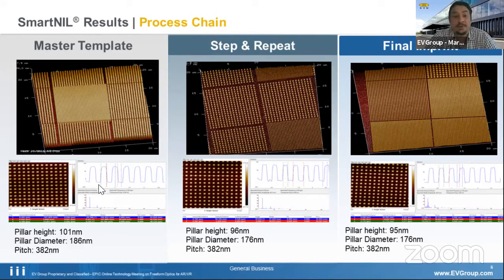Just to show it in terms of nanostructures, which is basically a zoom in to the structure you have seen in the previous slide, which was the Stuttgart Castle. You have here nanostructures. As a reference, roughly a size of 100 nanometer height and 100 nanometer diameter. And you can see from the master template to the step and repeat imprint and to the final imprint, there's just a minimum deviation. And the deviation we have is related to shrinkage of the polymer materials. This is a common thing that's well known for any molding process. Also thermal molding processes need to live with some deviation from the master. However, it's stable and can be biased, and that's the nice thing.